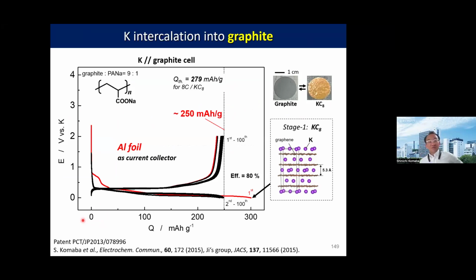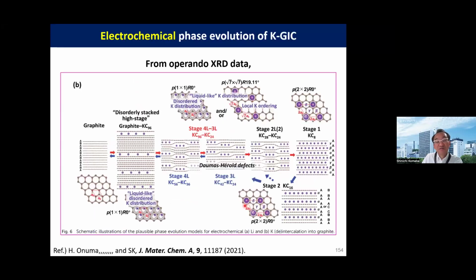For the negative electrode, graphite is the best choice. After careful investigation of bulk chemistry and interface chemistry, and also using aluminum foil as current collector, we see highly reversible potassium insertion and extraction, with reversible capacity over 250 milliampere hours per gram, and the stage 1 KC8 is formed after full charging. From operando X-ray diffraction, we have already reported details of the insertion mechanism. And please note that during potassium intercalation, the Daumas-Hérold model can be applied, similar to the lithium case.